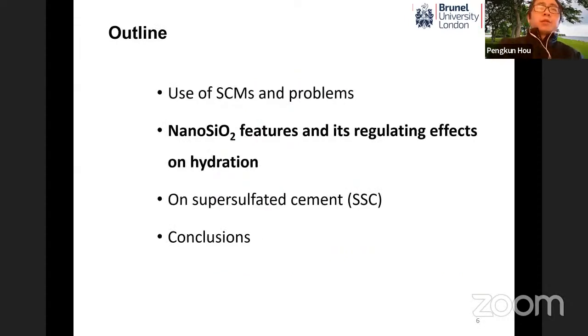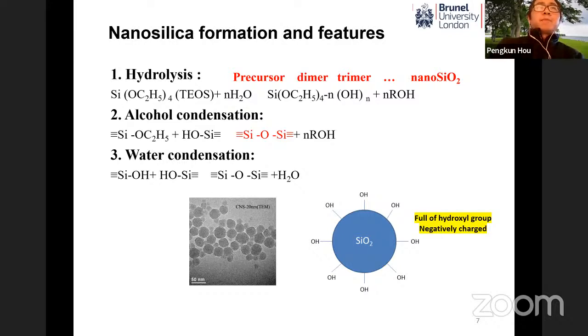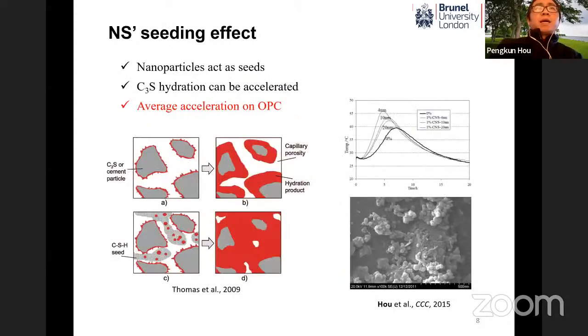In the last 10 to 20 years, bunches of research have been conducted on using nanoparticles such as nanosilica to improve the properties of cementitious materials. When we look at the production of nanosilica, generally it's 3 steps: the hydrolysis of the precursor such as TEOS, and then the alcohol condensation and the water condensation happen, and then the silicon dioxide molecules grow together, forming dimers, trimers, and the nanosilica, which is less than 100 nanometers. This nanoparticle is characterized by being full of hydroxyl groups outside, and it is actually negatively charged.